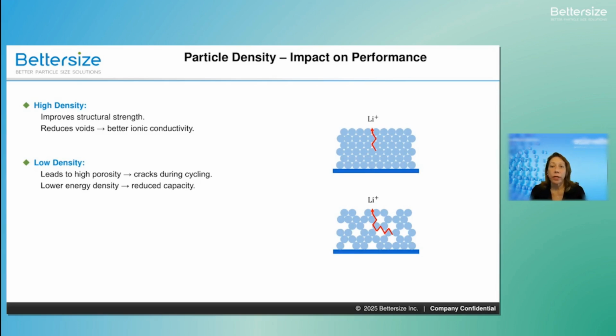High-density powders improve structural integrity and reduce voids, which enhances ionic conductivity. Low-density powders create porous structures that crack under cycling stress, and lower energy density. This is why density control is as important as particle size optimization.